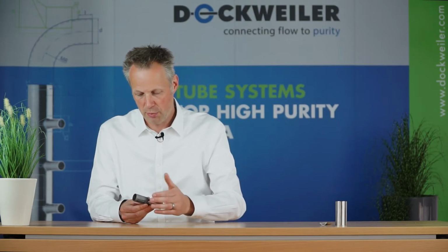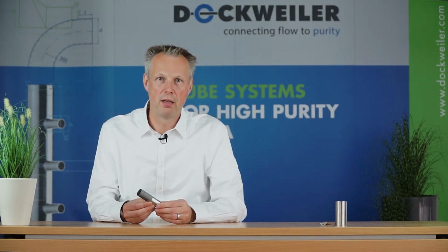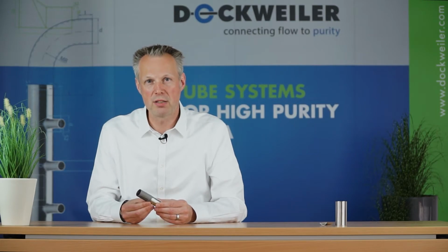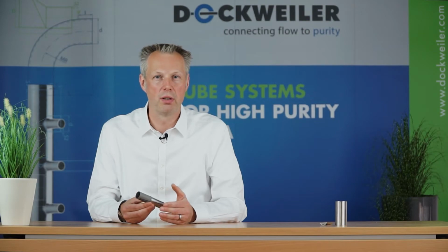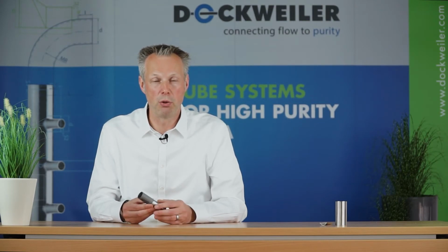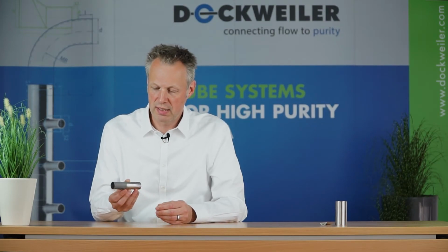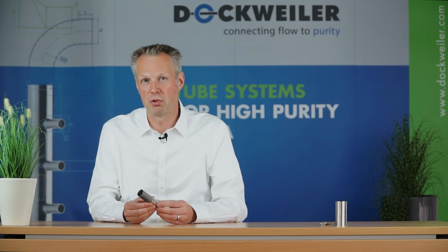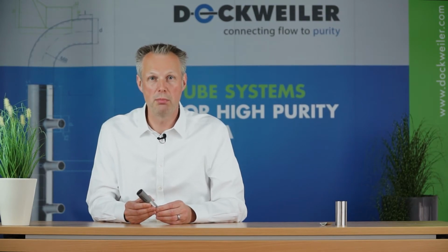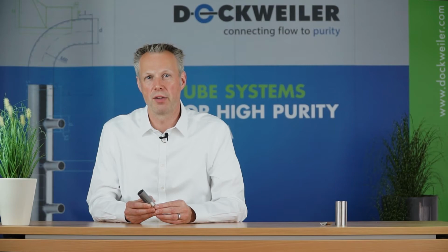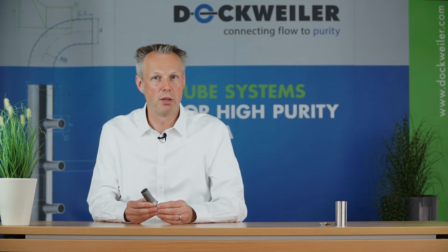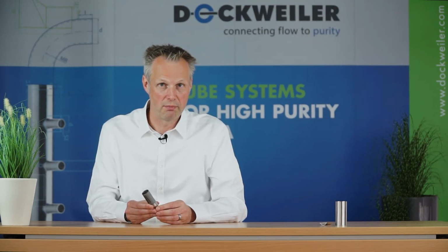You see carbon being diffused in the grain structure of the alloy, taking out the available chromium and forming chromium carbide in this alloy. And that's what you see here on the top. So you can ask, is it a problem? Yes, it is, because the chromium itself is not available to protect the surface anymore.